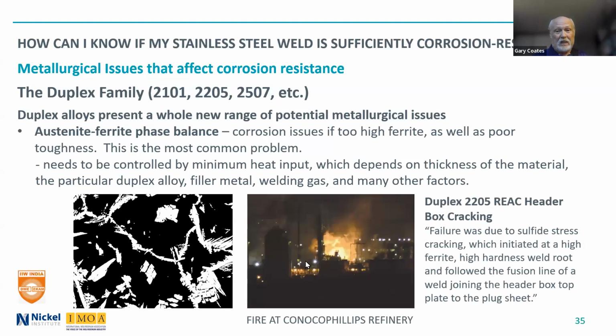This is a fire that happened at a refinery because one weld in duplex cracked, sulfide stress cracking. It was a weld where they were welding thin material to thick material, and they didn't do any special welding tests on it, either as a qualification test or as a production weld, and it cracked, caused a fire, millions of dollars in damages. There have been other fires at other refineries that have had the same issue, and people have been severely injured and even have been killed. So when duplex is good, it's very good. When it's bad, it can be very, very bad.